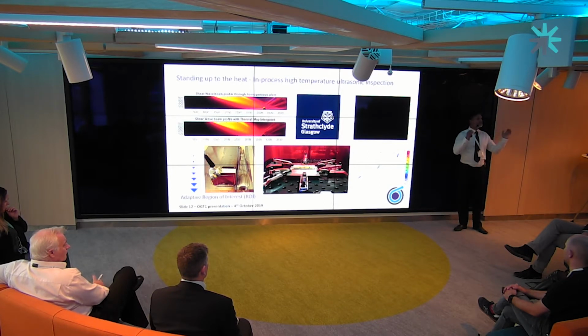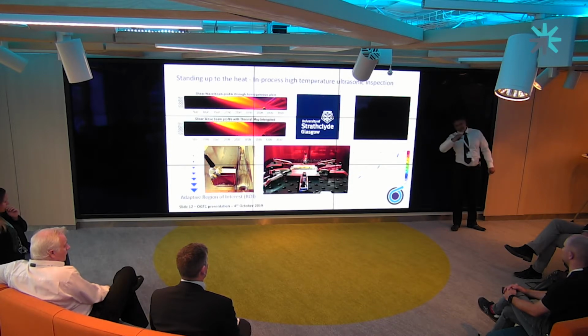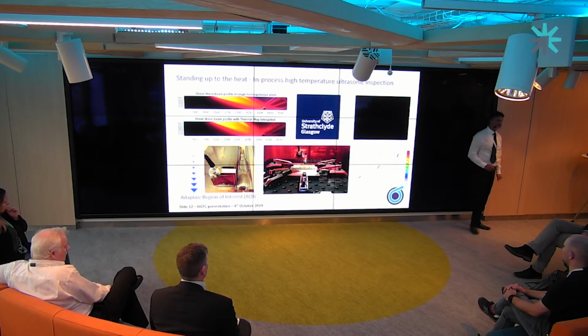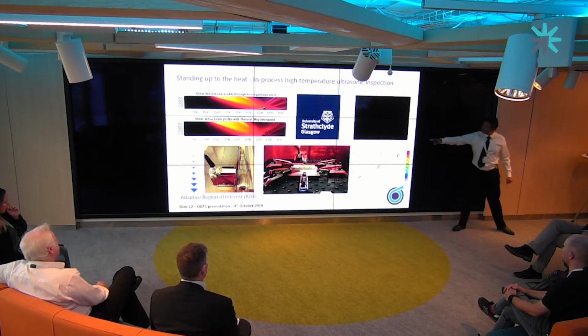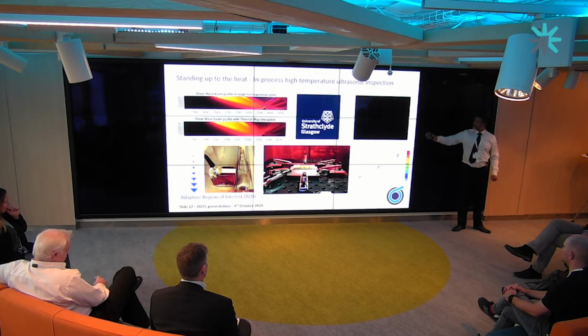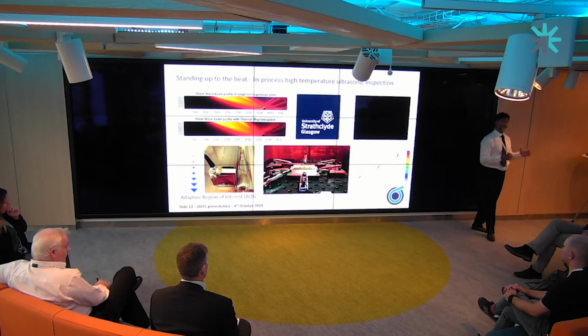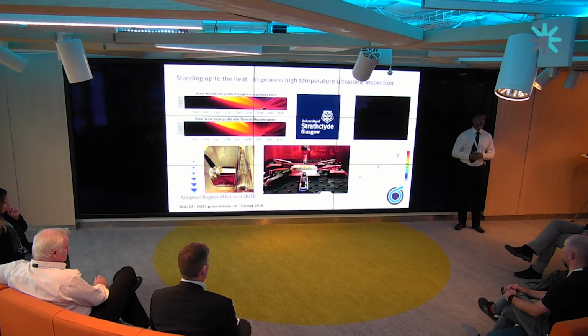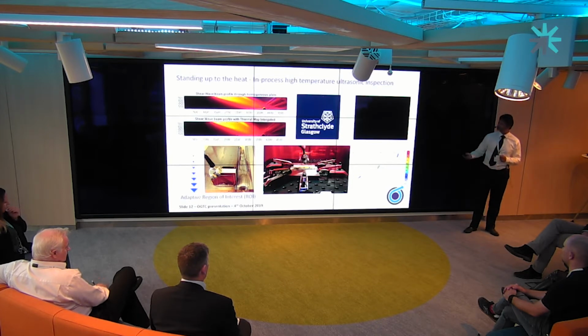The trouble is with heat, like everything else, it's a bit like diffraction. So the shear wave that comes through is distorted by the heat. So sound is distorted by heat within the structure. So we need to offset that and find out how accurate we are by finding that position. We can't wait for it to come down to room temperature. It becomes quite long. It becomes exponential in its thermal response. So it's very important that we try and get that done soon. And Charles McLeod and the team at Strathclyde, if you don't know Charles, I recommend you get over to Strathclyde and start looking at some of the excellent work they're actually doing there.